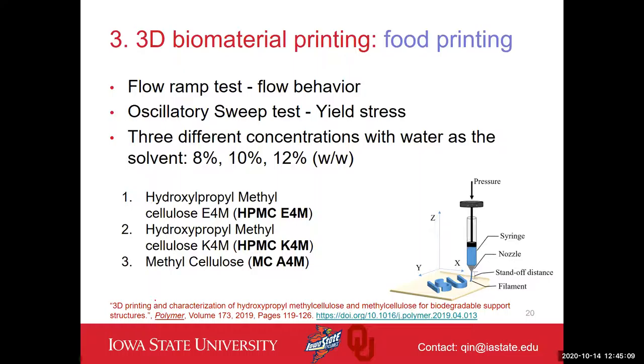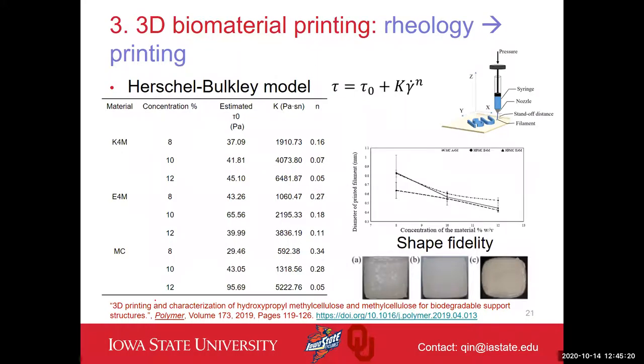We test the material at different material-over-water concentrations. And then for the rheology property, very similar to what we did for the concrete material, we also ran the rheology test to first identify the Herschel-Bulkley model that can describe the rheology property of the cellulose material. And then we identified a viscosity range that is good for 3D printing, that has demonstrated good printability based on printing in that range.